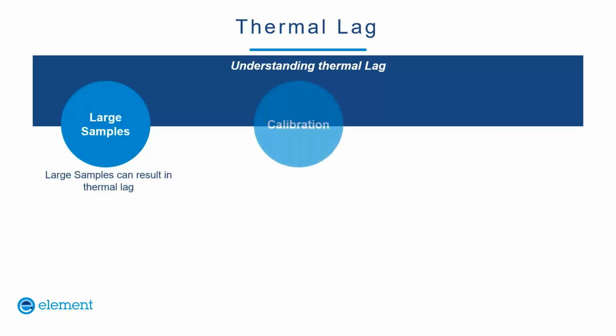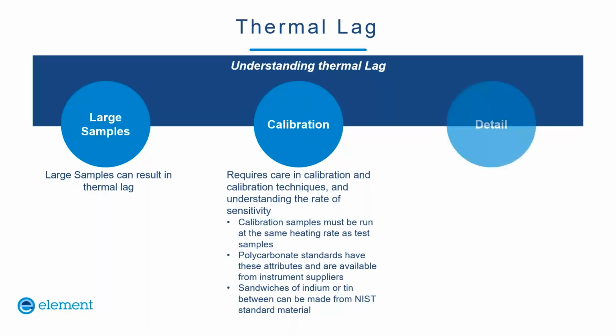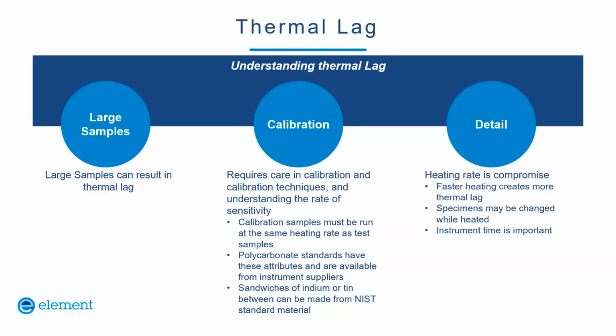I also want to talk a little bit about thermal lag. Thermal lag is important to consider in any thermal analysis, but especially DMA, because DMA specimens are usually the largest. The instrument measures the temperature of the air adjacent to the sample or just touching the outside surface of the sample. As the instrument heats, it takes longer for the center of the sample to reach temperature. Because of this lag, it's important that the calibration be performed at the same heating rate as the sample. Ideally, it would be performed with a material that's the same size, mass, and thermal diffusivity as the test material, but generally this isn't possible.